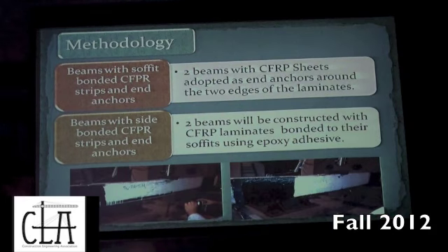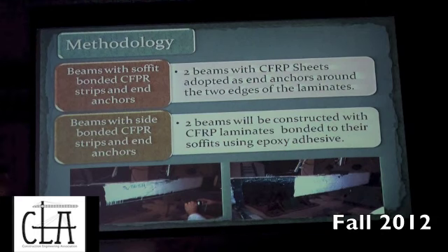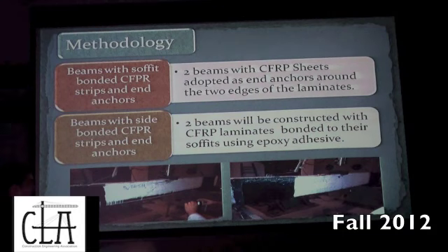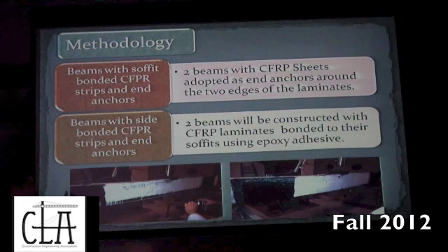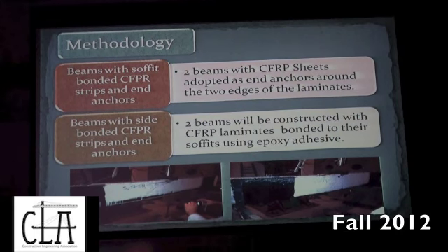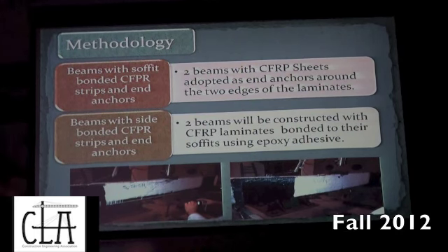We decided to have 4 more beams, 2 attached from the side and 2 attached from the bottoms. And at the same time, we're going to add CFRP sheets as the ones we handed out to attach them from the side. These should work as anchors and try to, again, delay the crack happening in the epoxy layer itself.